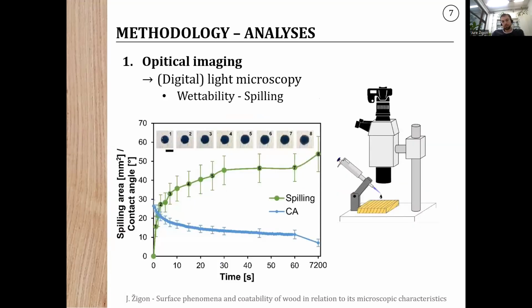Another usage of light microscopy can be to monitor the wettability or the spreading of droplets after application on the surface of wood. Not only again measuring the contact angles, but the spreading area, measuring the area over which the droplet spreads after the application during the time, of course. Here on the right side, we can see an example of how in this study the microscope was positioned above the sample where the droplet of the coating was applied.